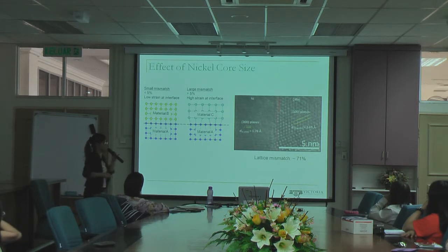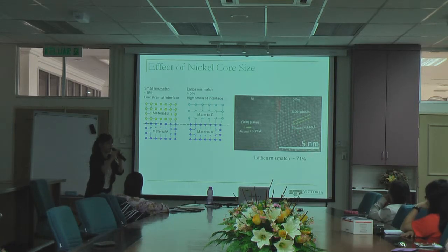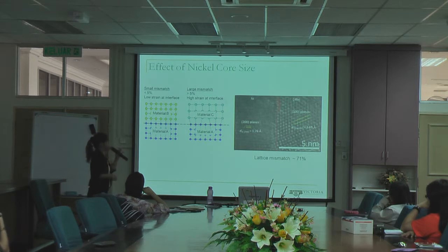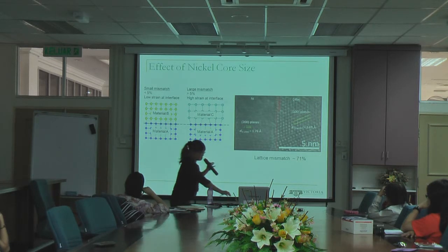When this happens, two things tend to take place. One is that the cadmium selenide will try to minimize the contact with nickel in order to minimize the strain. The other is that the size of cadmium selenide will be limited to a small size, because the greater size it grows into, the more strain there will be at the interface. That helps to explain why we are seeing the structures on the 40 nanometer size and 20 nanometer size particles.